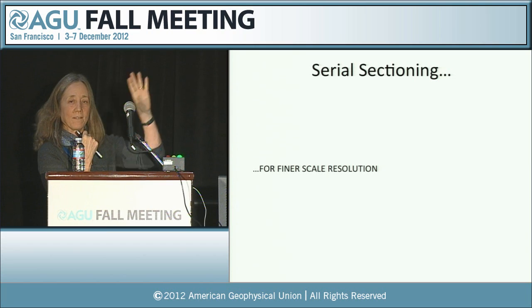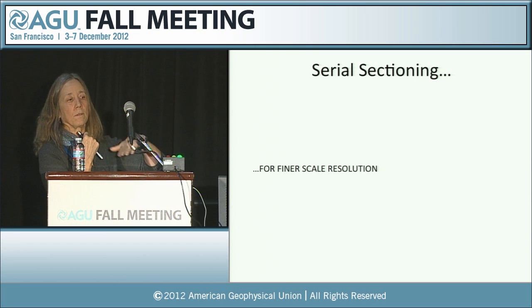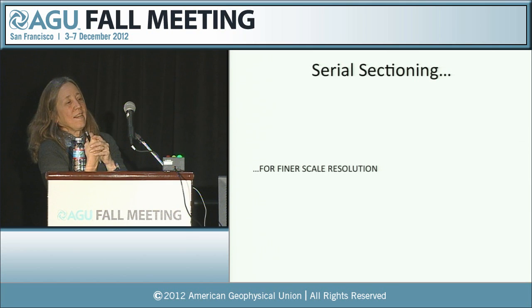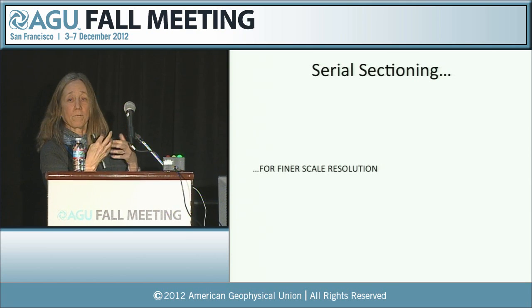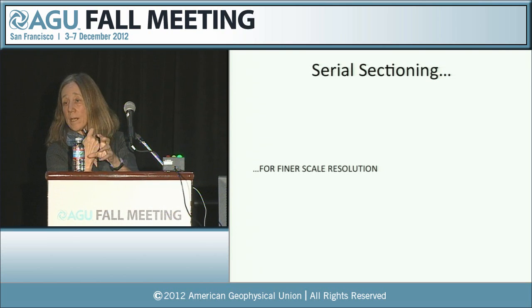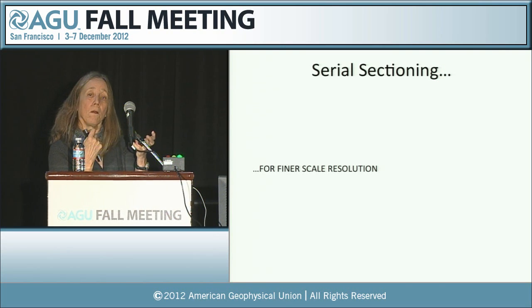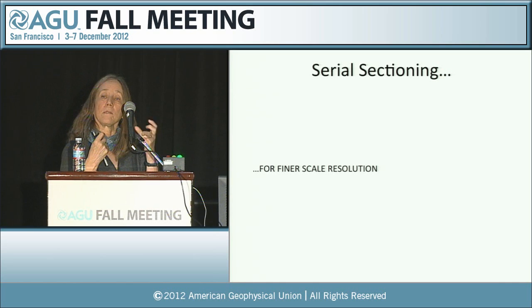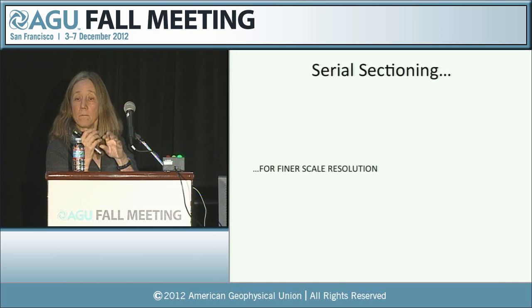So there's a nice orderly sequence of ages going inwards into the crystals, in the same way we saw with quartz. Our results really seem to corroborate the previous results we got from the cross-sectional analyses, that there is older zircon growth buried within these crystals. The challenge then is trying to reconcile the single crystal analyses with the depth profiling analyses, the ion microprobe analyses.